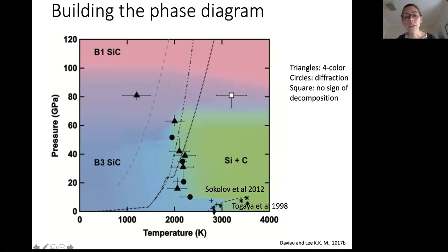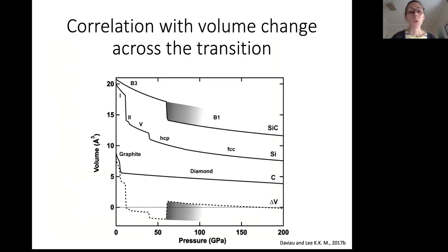Right, and so this is kind of a weird shaped phase diagram, with the lower pressure data way up at higher temperatures, and then our data all falling somewhere around 2000 degrees. And so in order to try to make some sense of this data, we made a plot of pressure versus volume of all of these different phases, and then looked at the volume change across this transition, so going from silicon carbide to silicon plus carbon. And what we find is that all of these phases have very dramatic volume changes as you go up in pressure because of solid-solid phase transitions.